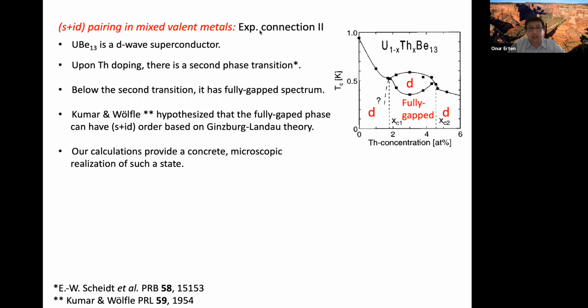And of course, we are not saying what we did fully explains uranium beryllium 13. It's a complicated material with spin orbit coupling, different uranium multiplets, etc. It has some non-Fermi liquid behavior, two-channel Kondo effect, etc. But our mechanism, having this intermediate coupling to the conduction electrons, quite generically gives you s+id pairing. So it gives you one way of generating this fully gapped pairing from microscopic calculations.